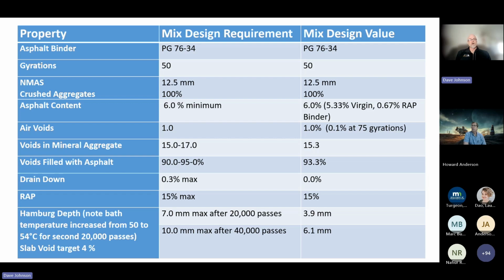As mentioned, it is a 12.5 millimeter nominal maximum aggregate size. This is a hard rock quarry. It's 100% crushed material. The binder minimum requirement is 6%, which is exactly where this mix was designed. The air void range now is 0.75 to 1.25% air voids. 1% was what this was designed at. And just FYI, if it was taken out to 75 gyrations, it would essentially be a 0 air void mix.